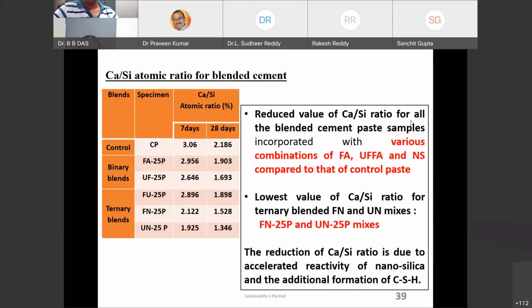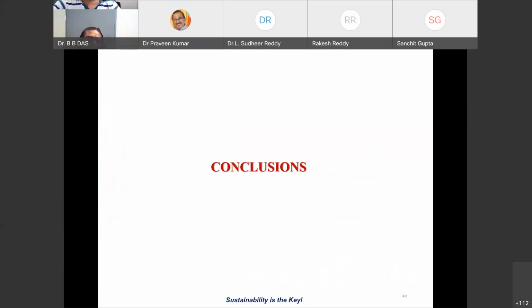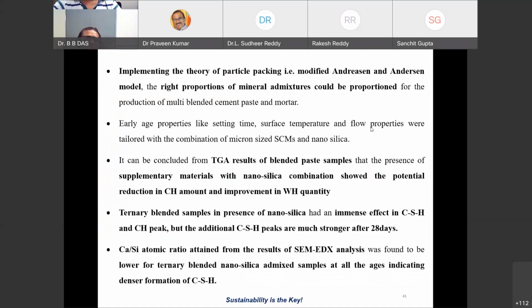So the reduced Ca/Si value for all the cement samples incorporating various combinations of fly ash, ultrafine fly ash, and nano silica is the best. Whatever the case, at this point of time, don't go for control tests or a control OPC-based cementitious model. Remember, this is very important. Even if you cannot afford nanoparticles in the mix, go for binary blends. That is essential at this point of time. The lower Ca/Si value is due to the accelerated reactivity of silica and the additional formation of calcium silicate hydrate.